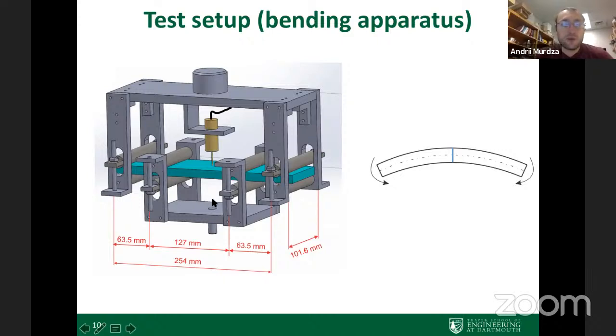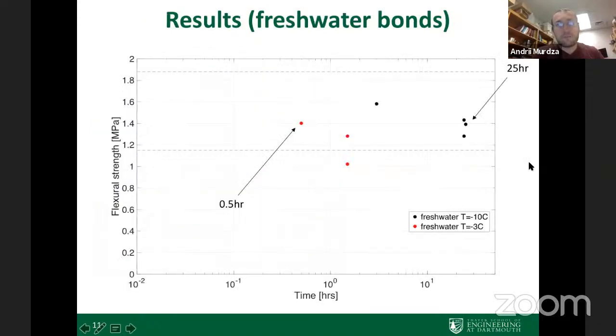This 4-point bending apparatus allowed us to bend our specimen in the following way, as you can see. Initially we used the freshwater bond. We sprayed with the freshwater fine mist, then brought these two parts together and waited for a time ranging from about half an hour to up to 25 hours. And then after that, we measured the strengths.